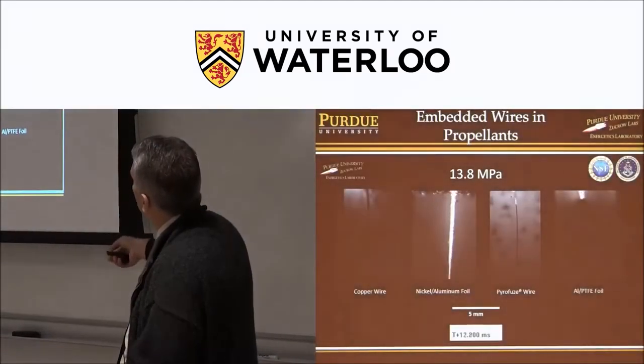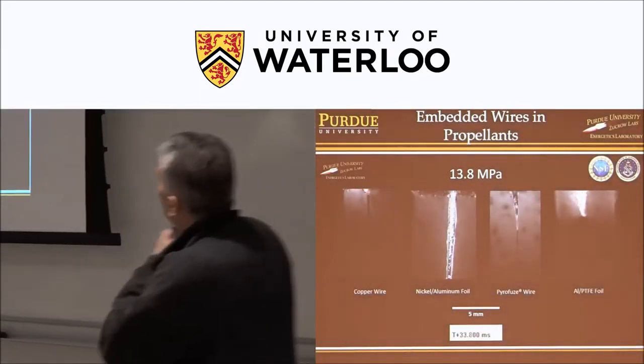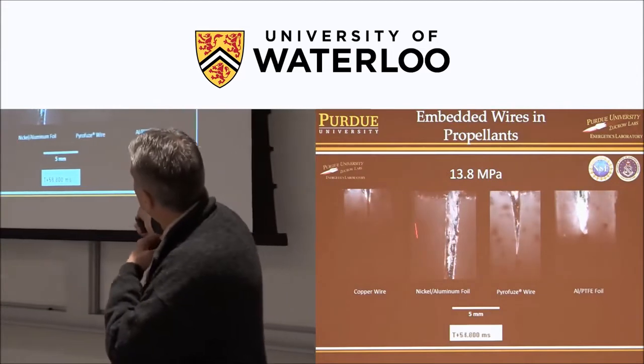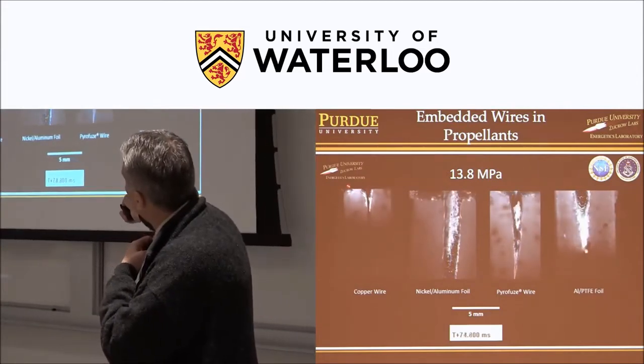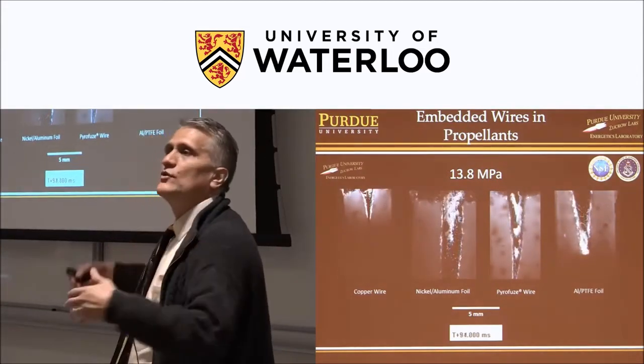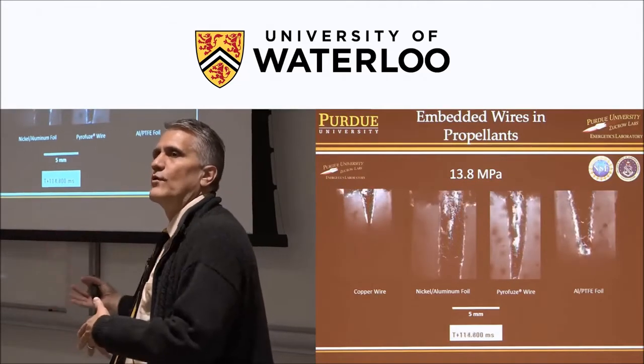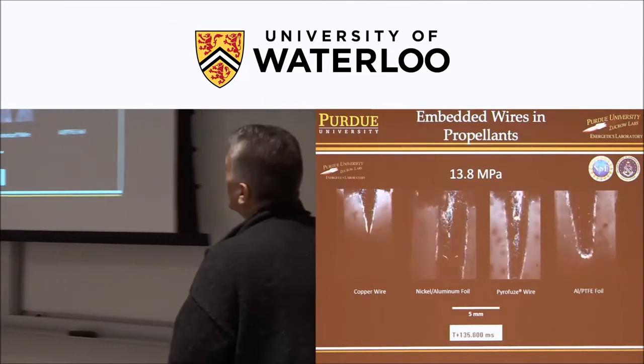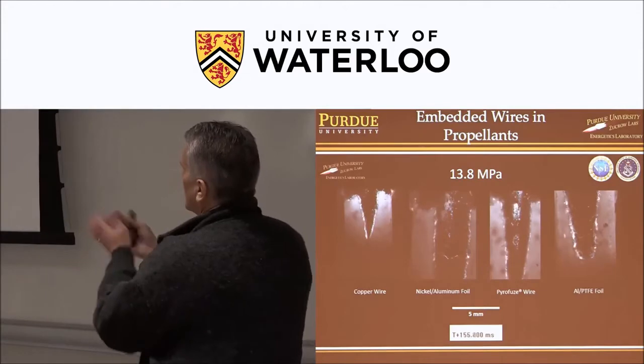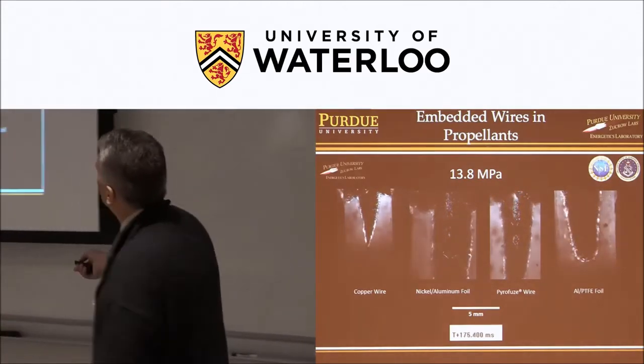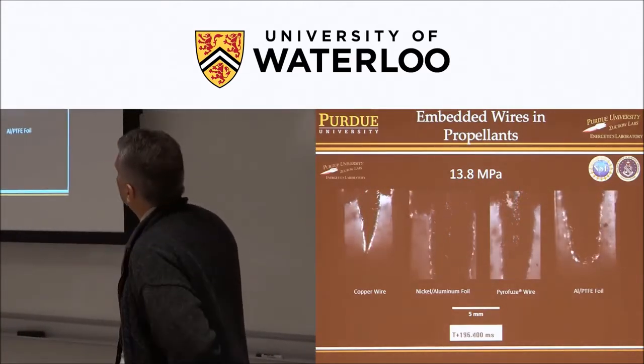And this is a video of four different tests. On the left is the baseline copper wire. You can see how it forms this V. That increases the surface area and therefore increases the effective burning rate. So higher surface area that regresses back means that you'll have more of that propellant burning up at a faster rate.